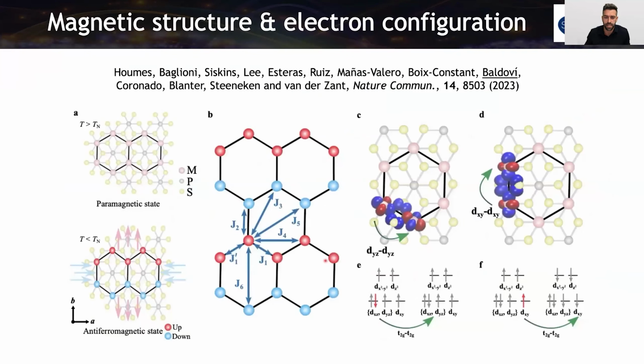And we were doing this orbital-resolved approach to see what is happening with the ferromagnetic interaction. That is the main interaction here along these two atoms, along these two irons, for example, in this case iron, and along these two irons. So the material has this zigzag distribution. So in principle, this is antiferromagnetic and this is ferromagnetic. If we take into account this ferromagnetic interaction with the compression of the axis, we are favoring this mechanism, the hopping of this electron from this orbital to this orbital. And in the case of the other pathway that is parallel to this b-axis here, we have the expansion of this axis because it's avoiding this, making this more antiferromagnetic, and is canceling this process.